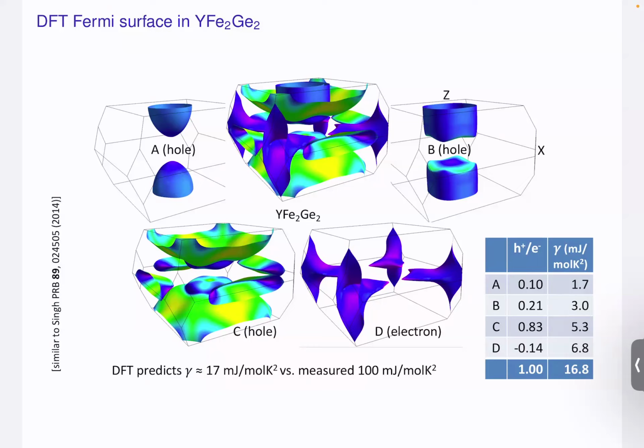And the DFT calculations also say we should expect about 17 millijoules per mole Kelvin squared heat capacity, but what we measure is 100. So there's a mass enhancement we need to understand.